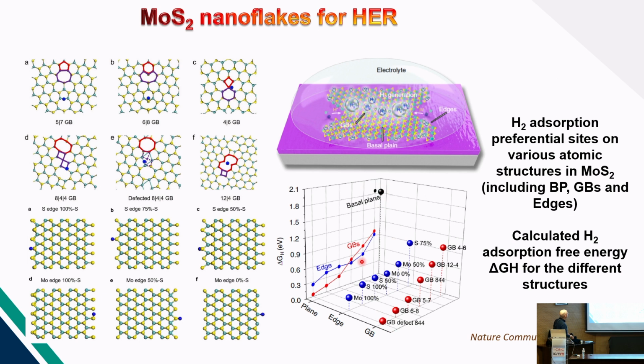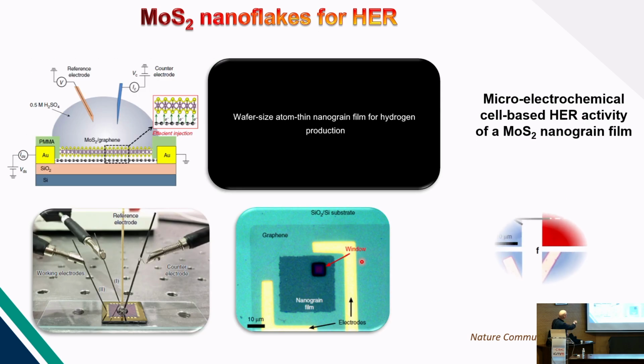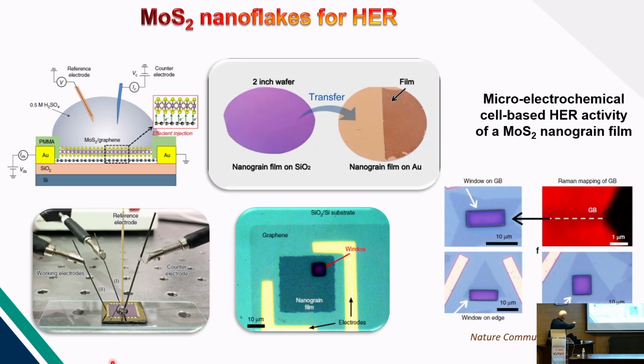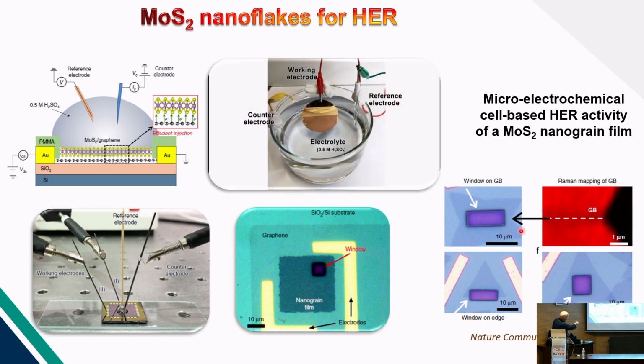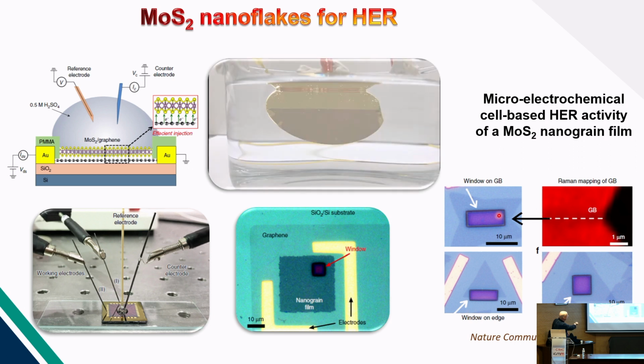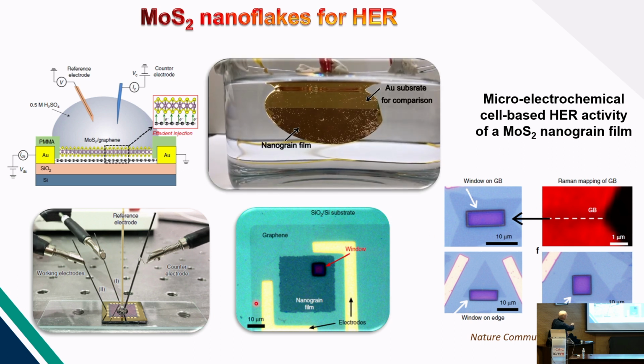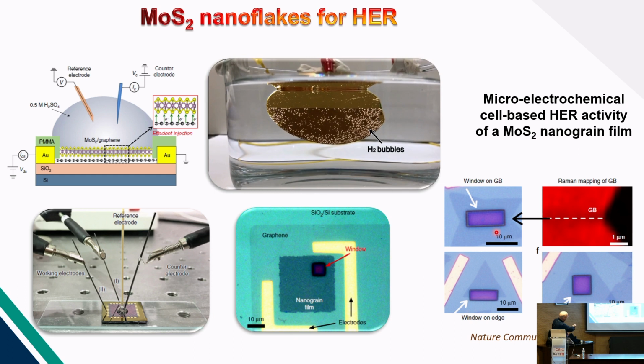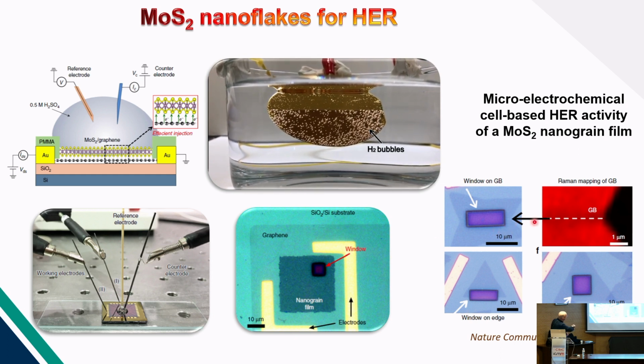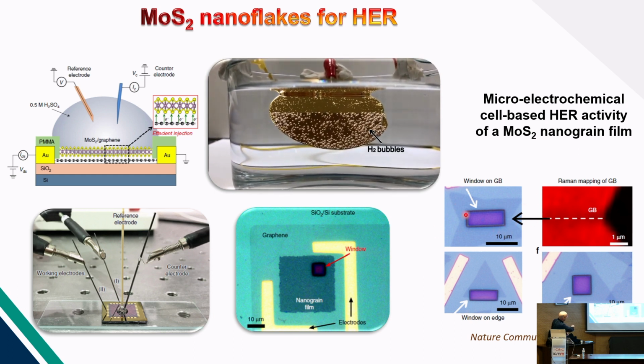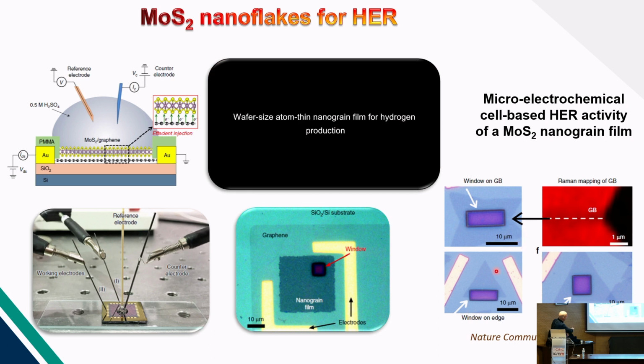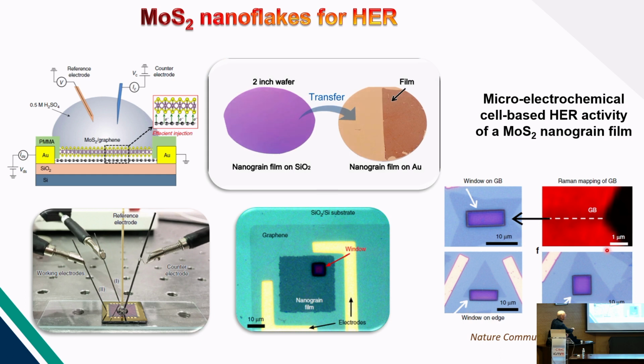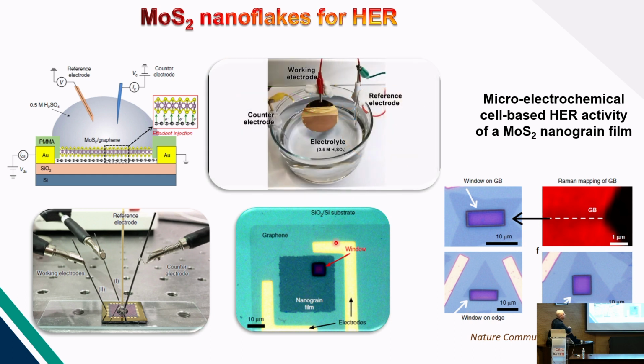So what you can do is just, in this case, create this cell here, and with these windows, what you are doing is trying to measure the electrocatalysis only inside the window, because it's protected, all the rest. And the nice idea is that you can measure one grain boundary, one single grain boundary. You can measure one single edge, or you can measure the basal plane. Or you can go to one of these multi-grain boundary materials, like this one, and also measure it.